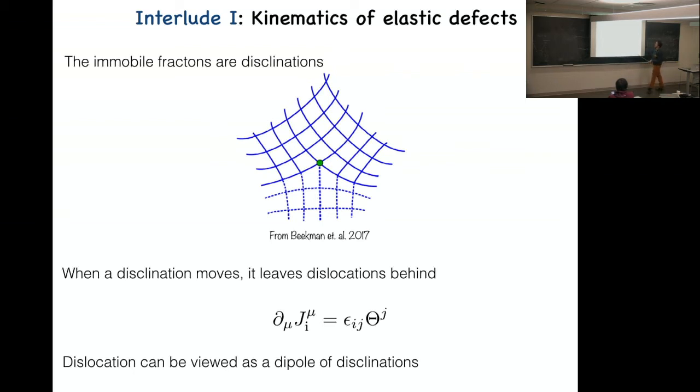The way you notice that there is a disclination is you start looking at vertices. You see here, every vertex is 4-valent, whatever the right word is. 4 links emanate from a vertex, 4, 4, and here 5. So there is a disclination here, there's a defect. Here is still 4, here is still 4, here is still 4, so there's a disclination that is localized here. Disclinations cannot move at all. Now, this is a bit difficult to visualize, but it's also known for quite a while that if you try to move a disclination, it's going to leave a trace of dislocations behind.